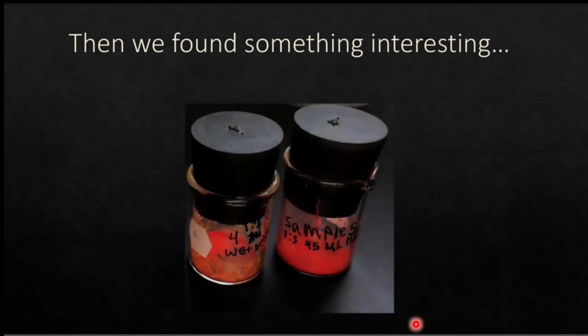But nonetheless, we put a cap on the beaker, put it on the shelf, and waited a week. And when we came back, we found that we had made this very dark orange, almost red compound. And when we did an X-ray diffraction on that, which we'll get to, we identified it as being this red polymorph of the copper iodide pyrazine system that had previously been reported by doing acetonitrile solution synthesis of these compounds, and then leaving the yellow product in acetonitrile for over a month. And when they did that, they got a very small conversion over to this red polymorph that you see here.